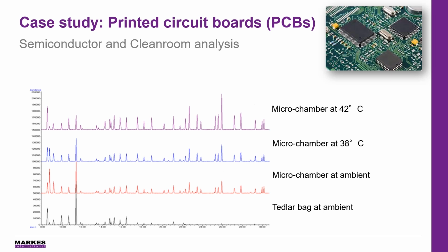So what we then did was take replicas of that sample and pop them into the microchamber. Even at ambient temperature, which is the second trace up from the bottom, you can see that there is a much better recovery of the compounds of interest. And if we elevate those temperatures, as you would expect, a higher emission rate is taken from those pieces of material. So you can see here just the ability to utilize the microchamber across a range of product conformity applications.